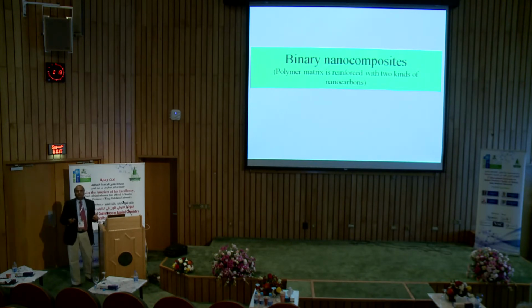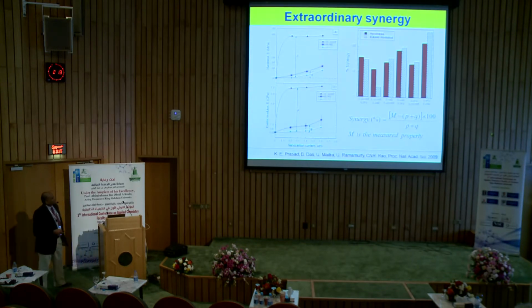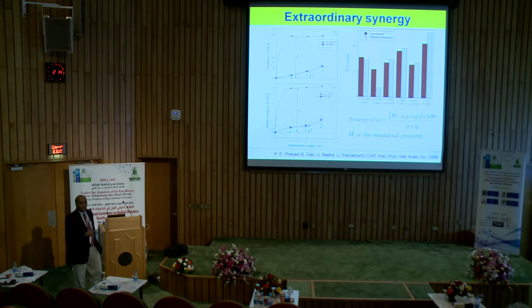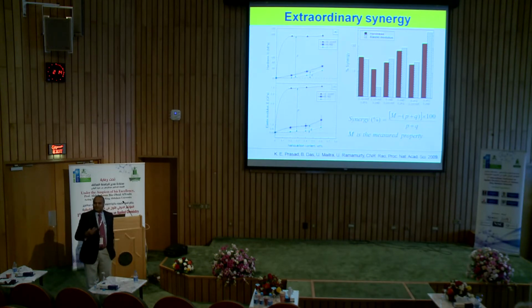Synergy means if I put 1 plus 1, and it is more than 2, that additional benefit is what we call synergy. Okay? So this is some work, again, somewhat old work, where we showed that these are for if you put only one material. For example, the blue is nanodiamonds, the green is few layer graphene. But if you put both of them together, you get an additional benefit, and that's what is plotted here. The extra benefit that you get. So if you put 1 plus 1, if it is 3, the additional 1 is what we get here.